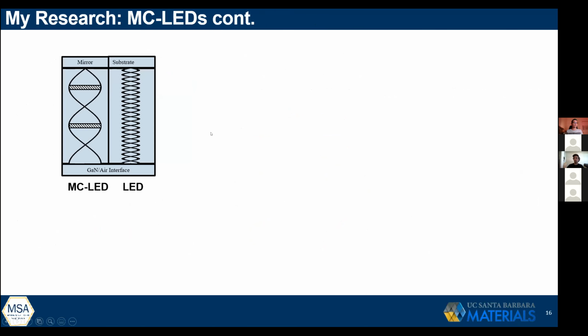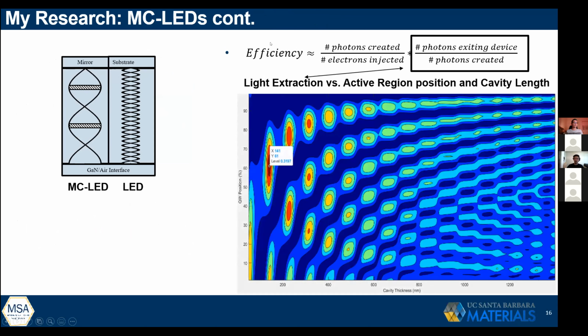And so what we can do is decide where the electrons get converted to photons in our device, such that we're able to achieve the wavelength profile that we want. Efficiency is a function of the number of photons exiting your device over the number of photons that are created in your device. This parameter is known as light extraction. And so what you can do is plot it for a given cavity length. In our example, we'll call it 200 nanometers or so, or 140 nanometers.